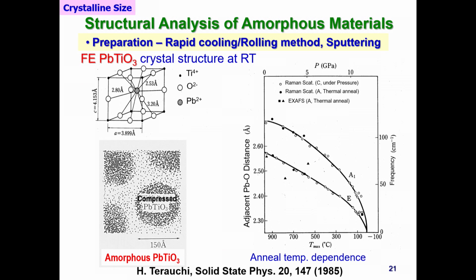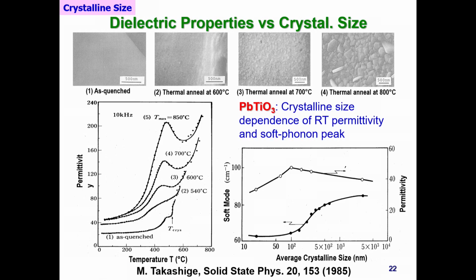That's the situation. But in parallel, starting from amorphous lead titanate, gradually increasing the temperature and annealing, making small particles. So in amorphous, the Pb-O distance is quite small, 2.3 angstrom, but in crystalline it is 2.6 to 2.8 angstrom. Therefore, if you create a crystalline particle surrounded by the amorphous, this squeezes dramatically. So high compressive pressure is created. That makes it more difficult to become ferroelectric. Okay? So with increasing annealing temperature and time, you can increase the crystalline size gradually. So parallelly, you can find a sort of Curie permittivity peak around here, okay?